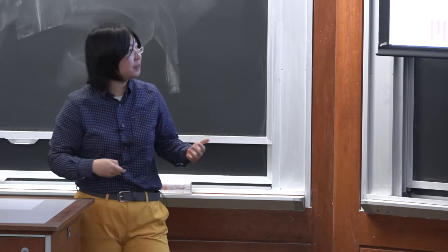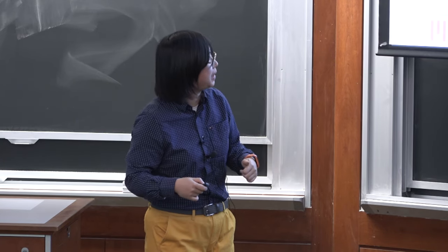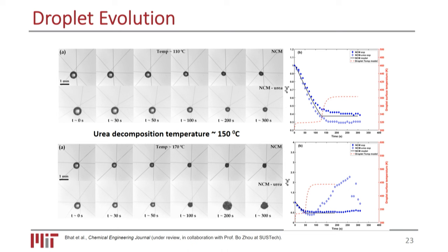And how does this compare qualitatively and quantitatively? We took those videos and did screenshots so we can track how the diameter changes with time and compare it with simulation. Essentially, we control the droplet to be as spherical as possible so we can make a one-dimensional assumption and then compare it with a single droplet evaporation model. For a single droplet evaporation under heated conditions, we expect to see a so-called D square law because it's a surface evaporation. The diameter squared versus time should change in a relatively linear manner. And that's what we see for both scenarios,